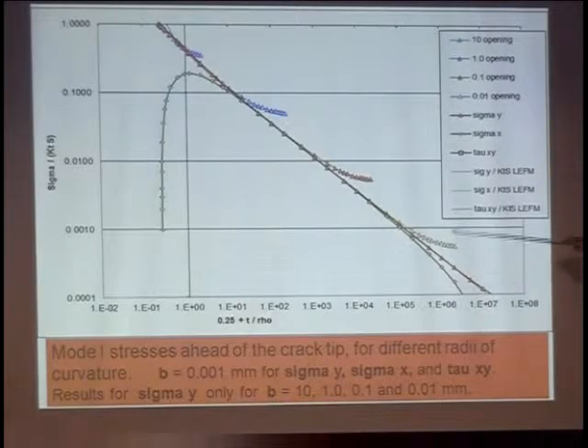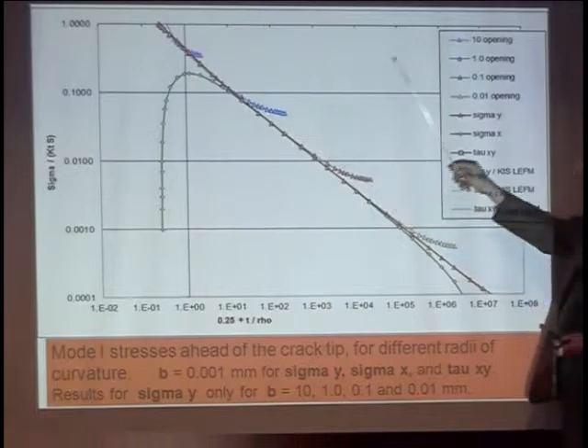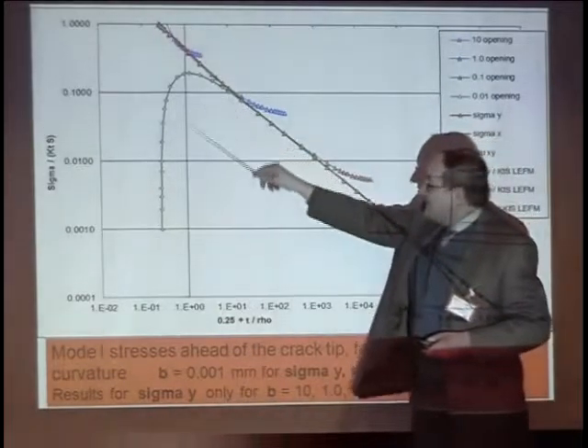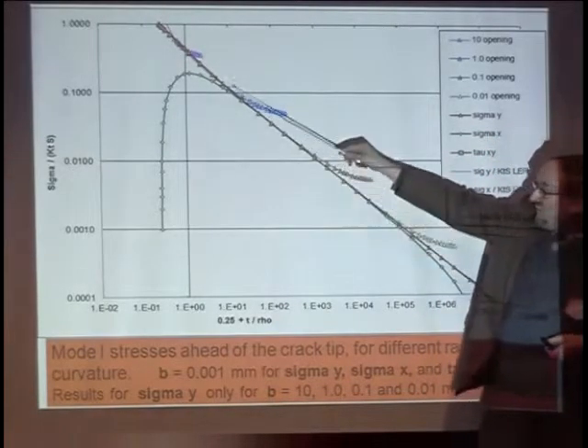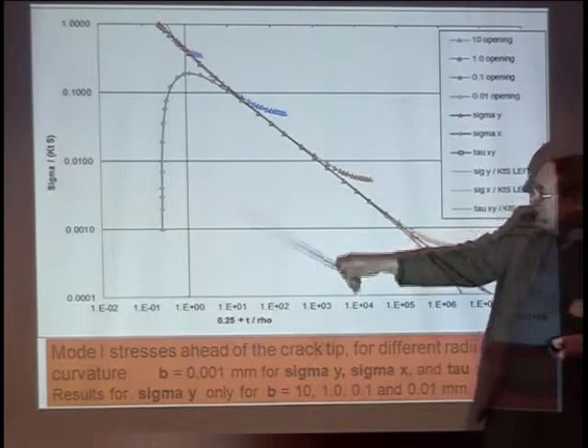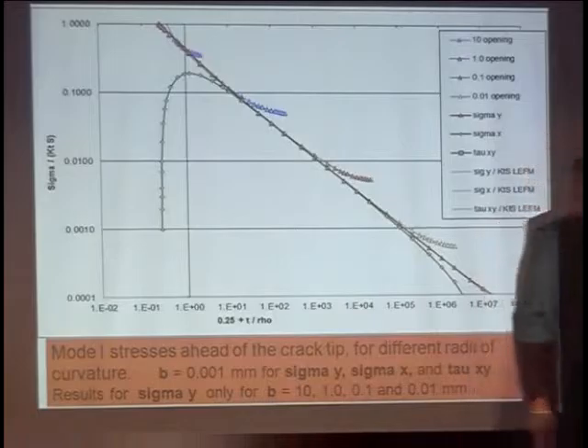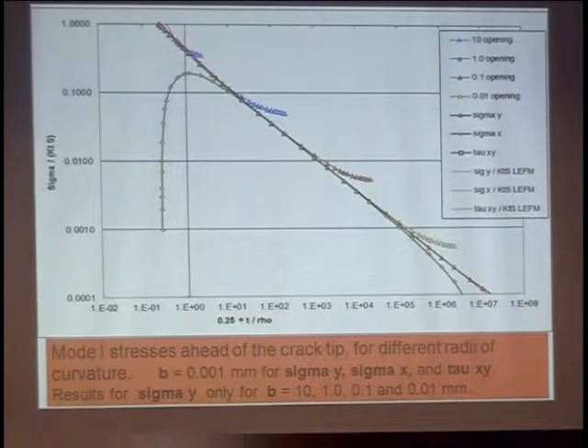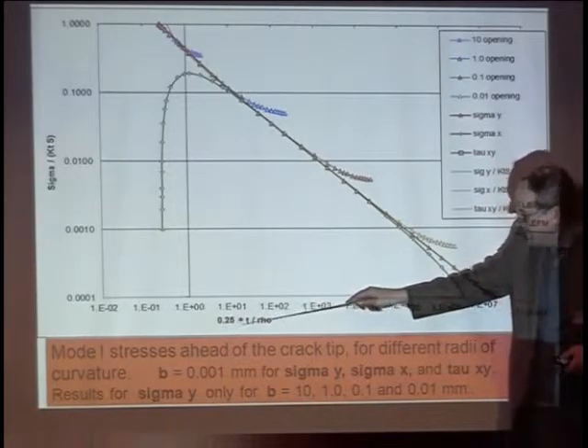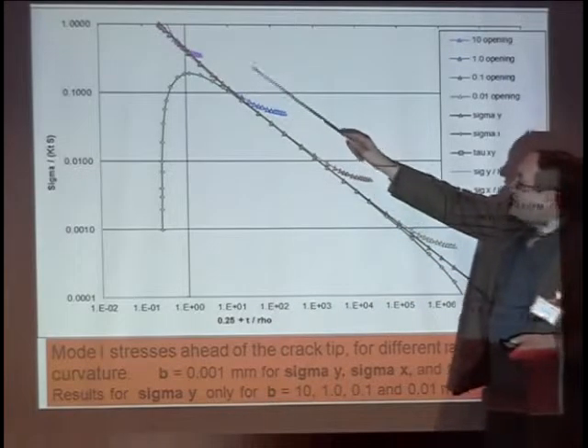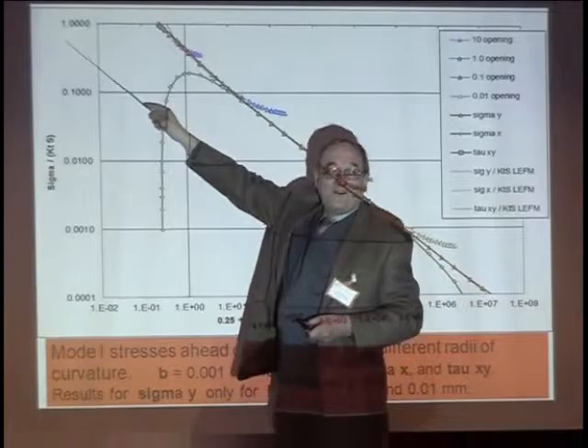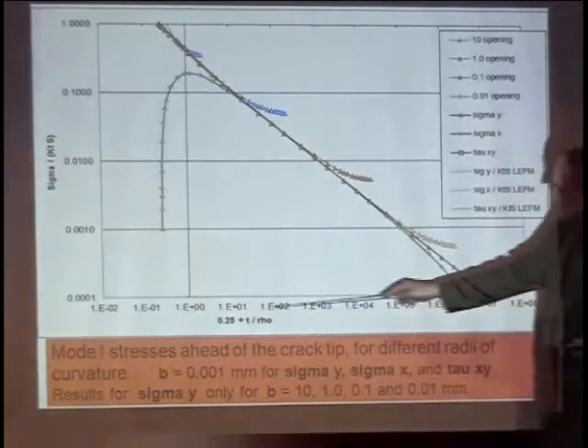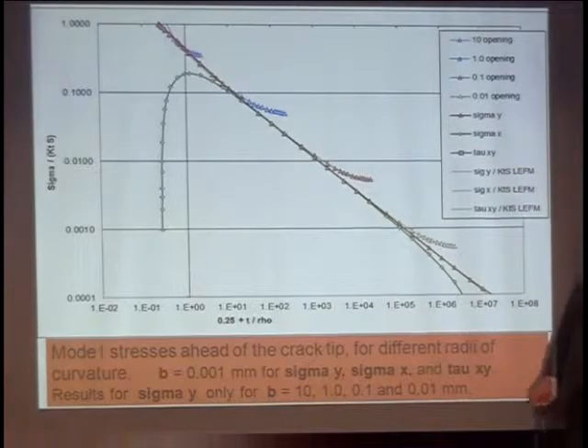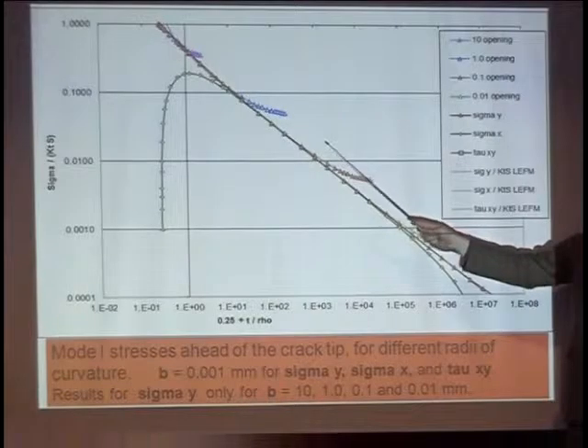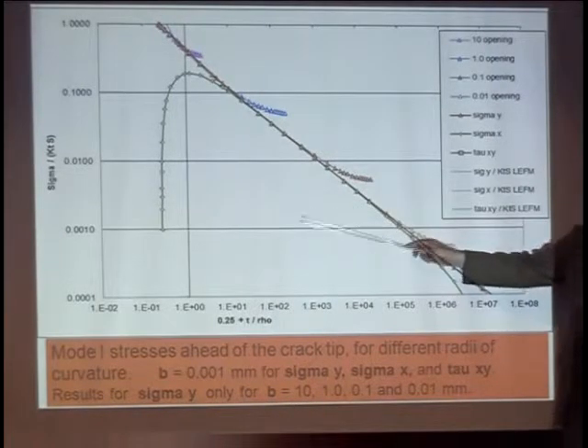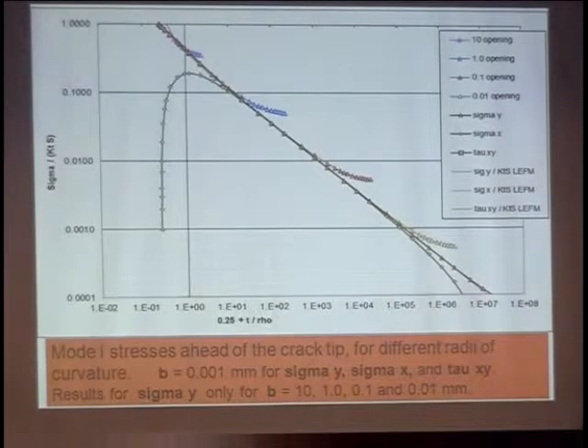But in the far field, of course, you get different results. And these relate to KT for each. But they all come to this line. The sigma x in green has to come down to 0. The one thing I've changed here is I've made it logarithmic on this axis. So it's more like the normal plots we see. We expect LEFM to give you a nice straight line of slope minus half, and there it is. The other thing I've done is I've added a 0.25 onto t over rho. And I've done that on purpose just to make this end of the curve straight. Originally it went across to 1 and went off to infinity in that direction. But by putting in a little fudge factor there, we can make the line straight. And if you remember Paris and Erdogan, which came up earlier today, they put in a factor much like that, only theirs was 0.50 rather than 0.25.